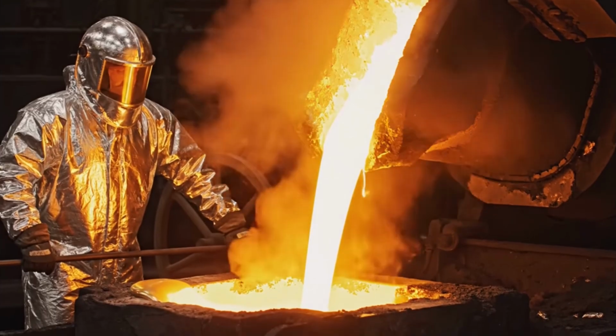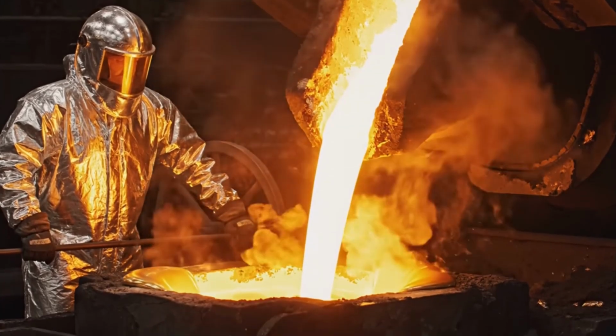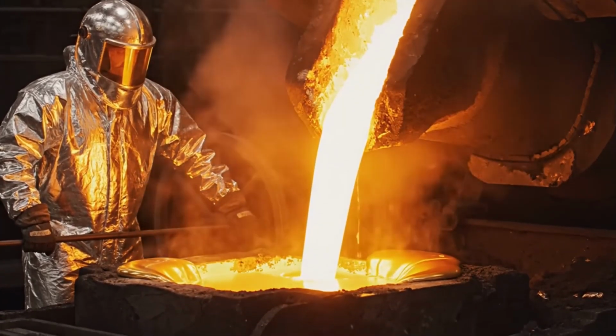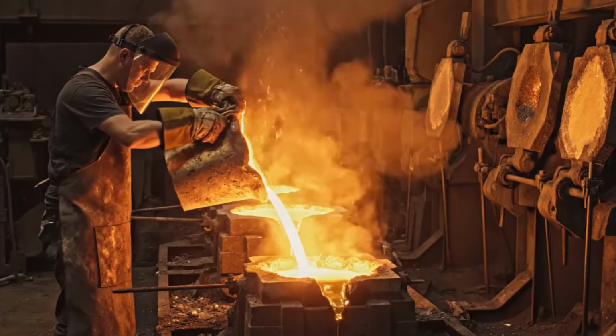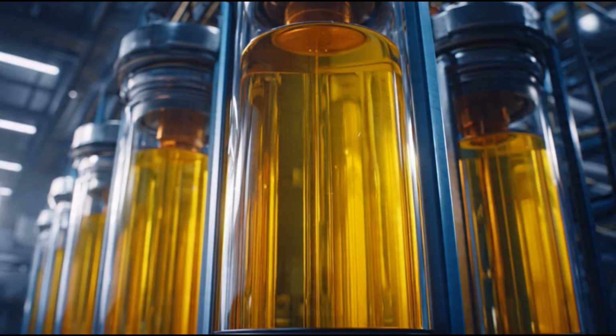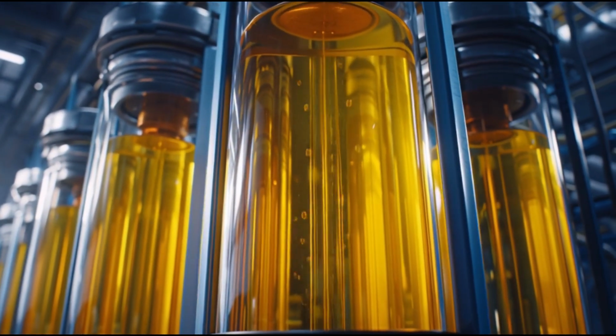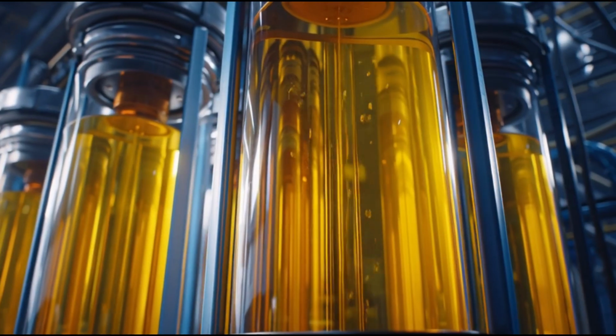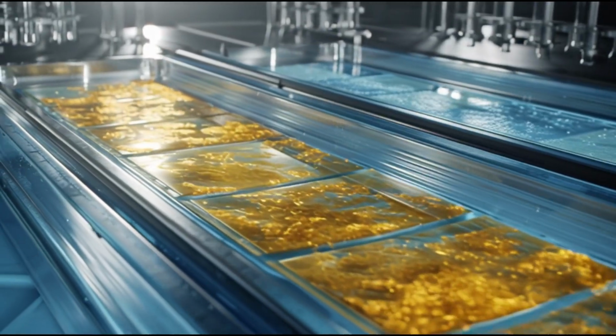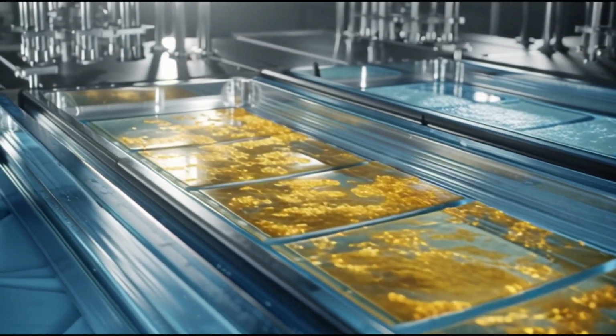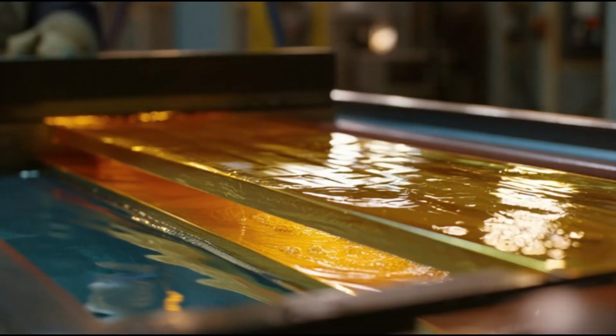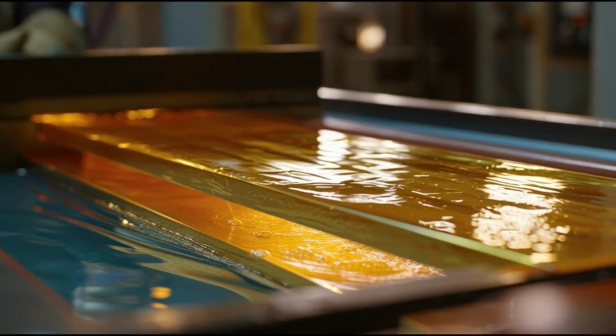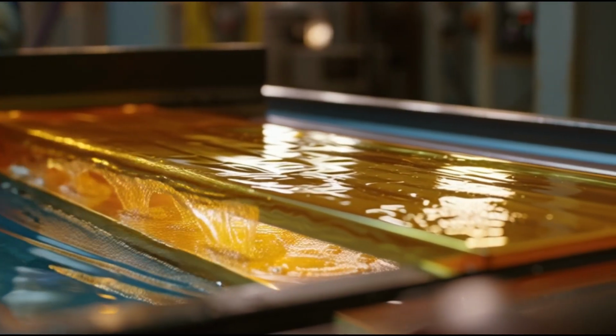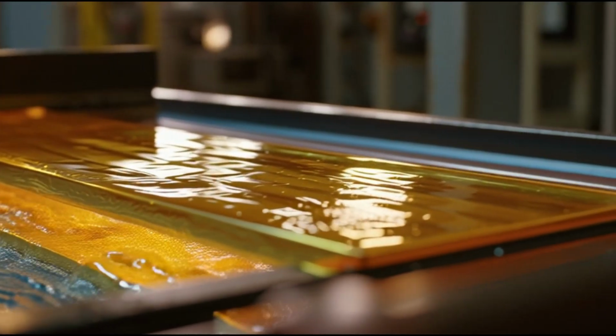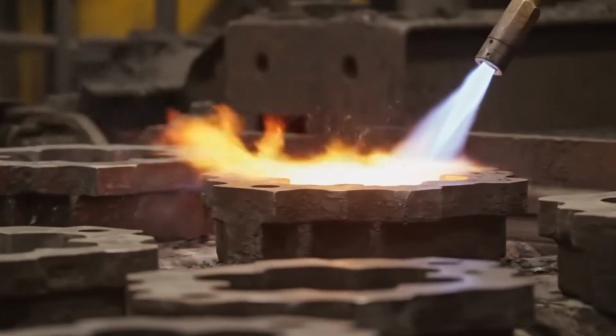To hit that final target of 99.99%, what the trade calls 4 nines fine, the gold goes through electrolytic refining. The still impure gold is cast into anode form and lowered into a gold chloride bath. When current flows through, pure gold releases from the anode and builds up on thin gold starter sheets on the opposite side of the cell with remarkable precision. What accumulates on those sheets is 99.99% pure gold, about as pure as it gets.